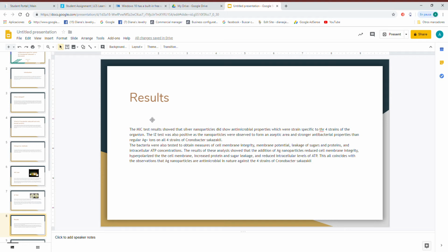So the results of this study: the MIC test results showed that silver nanoparticles did show antimicrobial properties which were strain specific to the 4 strains of the organism. The IZ test was also positive, and the nanoparticles were observed to form an aseptic area and stronger antibacterial properties than regular silver ions on all 4 strains of the Cronobacter sakazakii organism.